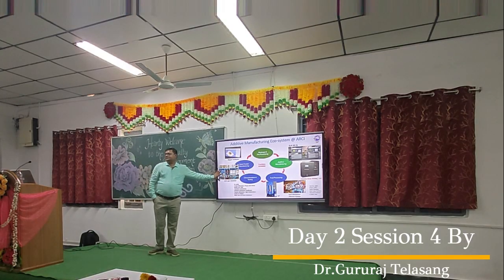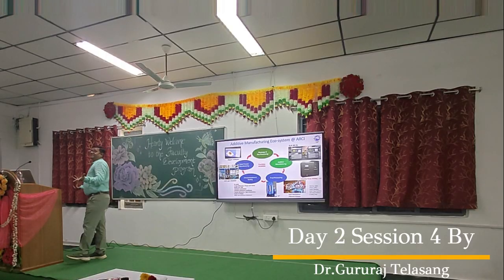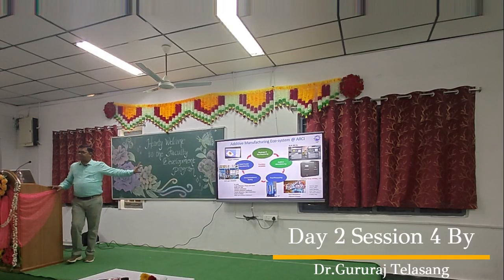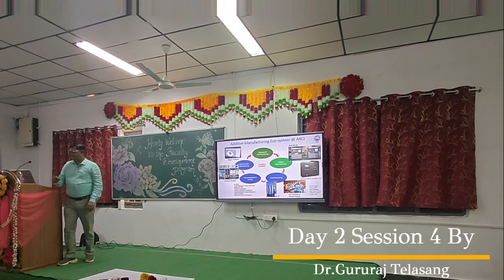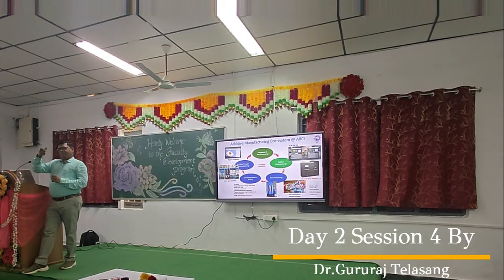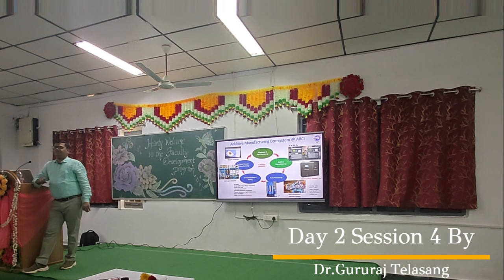This is something called an atomizer. I said powder, so where is it coming from? There is a process by itself. It's a two-floor setup. From the top we melt, then we spray the melt. Spray means, like during COVID time you used ethanol spray. Same way, we bring the liquid and with a lot of pressure spill it out, like taking water in the mouth and spraying. Same thing we do with metal melt. It becomes drops in a confined atmosphere, solidifies and drops. When it is coming down, obviously it is free fall, so it will be sort of spherical. We optimize it so that it will be spherical. Otherwise, it will be just a drop.